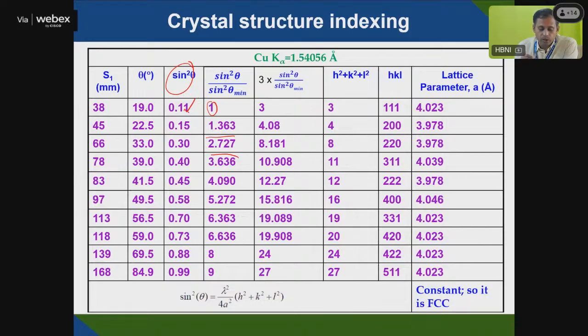After getting this, you have to get the nearest whole number. You have to multiply it by a number so that you get the nearest whole number. Like here, if you see this 1.363, I multiply by 3. Here you have to try randomly, 1, 2, 3. If you multiply by 3, then it's coming 3, 4.08, 8.1, 10.9, and so on. You know that for h square plus k square plus l square, if it is 1, 1, 1, you will get 3. The next is 2, 0, 0, so you'll get 4. So the nearest whole numbers we got here are 3, 4, 8, 10.9 into 11, 12, and so on.